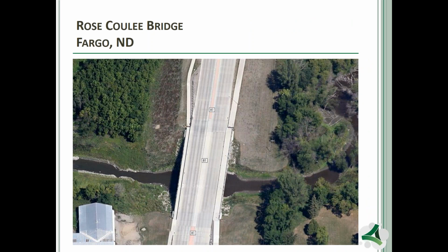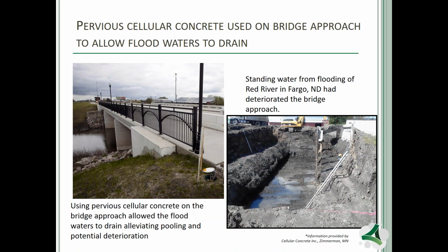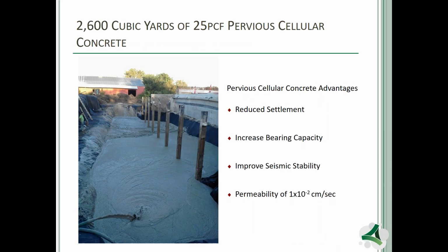On another project that was done in North Dakota, these are actually the completed finished abutments. These abutments had continual settlement issues, and the maintenance department in Fargo did a great job over the years in controlling the settlement scenarios, because before they dug it out, they had placed over 3 feet of asphalt in the abutment areas. The pervious cellular concrete was placed along the abutments and eliminated the settlement concerns in that area by reducing the loading on the native soils. They utilized 2,600 cubic yards of 25 pound per cubic foot cellular material.